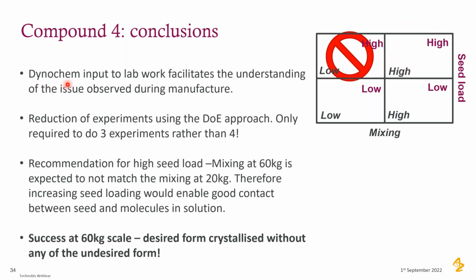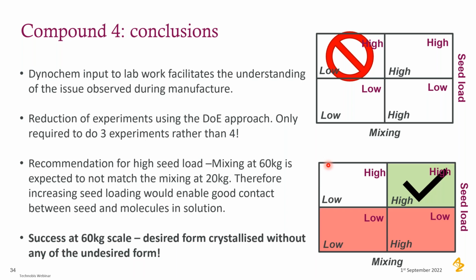So it was great to use DynoChem as an input to our lab work to facilitate the understanding of the issue observed during manufacture. Due to timelines, we focused our work only on the high seed loading and high mixing, and we thought that having a high seed with low mixing would not enable the seed to be nicely dispersed. So we would also have a problem of form control. So we thought best to just focus on the high seed and high mixing. And when we recommended that, we managed to successfully deliver in one go at 60 kilograms the desired form. So that was a great use of PAT and DynoChem to deliver the right form for that project for the next batch. So that was a nice story for compound 4.